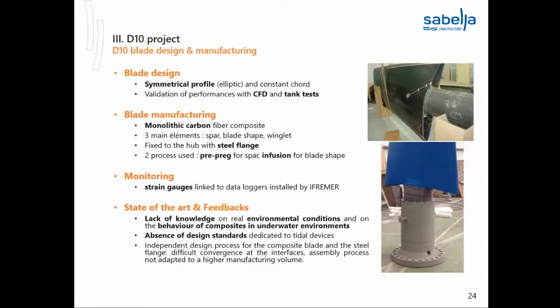For monitoring, we have strain gauges linked to data loggers installed on the blade by Ifremer. The state of the art when we designed this blade was a lack of knowledge on real environmental conditions and on the behavior of composites in underwater environments. We also had an absence of design standards dedicated to tidal devices. We used an independent design process for the composite blade and the steel flange, so we had a difficult convergence at the interfaces. The assembly process was not really adapted to a higher manufacturing volume. Next, please.